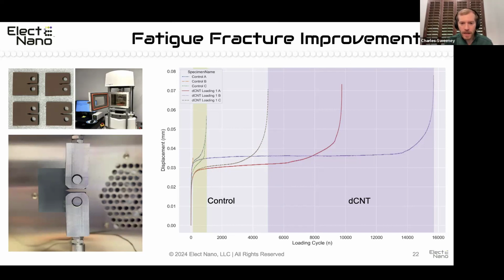The other thing is the crack growth mechanisms are far more stable. So the more vertical this line is, that means you went from no crack, no crack, no crack to boom, it failed rapidly. You really want to see that it takes a lot of energy to open up this crack progressively as energy is expended in breaking your component. And so the nanotubes really arrest the rapid progression of cracks and help to absorb a lot of energy during the actual fracture events.